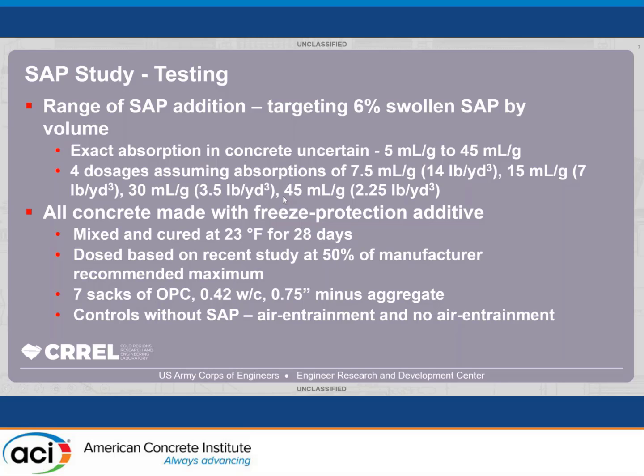The mixture that we used as our control and that we incorporated all this SAP into was a mixture that we had had a lot of success with during our previous study of using these off-the-shelf admixtures. And it's a combination of a non-chloride accelerator and a corrosion inhibitor. And our goal here was to use less than the manufacturer's recommended dosage, so you're not adding gallons and gallons and gallons of admixture. And so our baseline was a mixture that was 50% of that manufacturer recommended, that we had a lot of success with in a previous study.